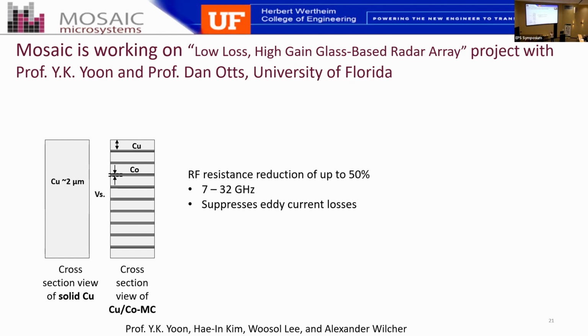If you're like me, you think, well, you're not going to do better than copper. But at radio frequencies, you can. So basically, having something like cobalt or nickel in with the copper alternating layers suppresses the eddy currents. And so in the 7 to 32 gigahertz regime, they've measured resistances of up to 50% less.